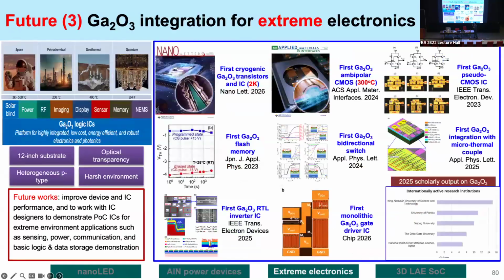And number 3, we want to continue to double down on the gallium oxide integration IC that we started, globally. So I earlier talked about the first gallium oxide ambipolar CMOS that can operate up to 300 degrees Celsius. And recently we published a paper where we report the first cryogenic gallium oxide transistor as well. And that transistor IC can operate at about 2 Kelvin, which is already below the background temperature of the deep space, which is 2.7 Kelvin.